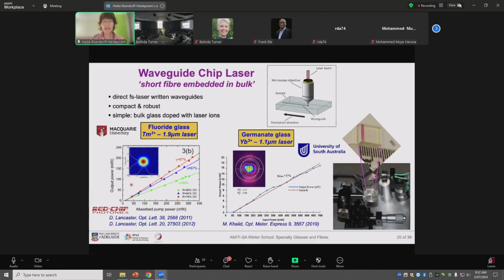This team started to work on making these waveguides into ZBLAN glass, using a femtosecond laser, making very compact waveguides and therefore lasers. They did this first with fluoride glass. This was then also commercialized by Dave Lancaster in the company called Red Chip Photonics. Then Dave and I also had a PhD student together, and she extended from fluoride glass to germanate glass, making an ytterbium chip laser.